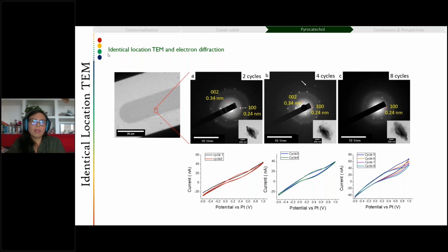And this slide allowed me to talk a little bit about identical location TEM, which is a known technique for electrochemists that typically use grids of TEM, put them close to an electrode for their experiments, remove the TEM grid every time and observe. We can do the same thing with the miniaturized cell, find at different times of the experiment the same particle or the same patch or the same region to evaluate different points of the reaction, which is not exactly operando, of course, but allows us to keep track of different points of a process.